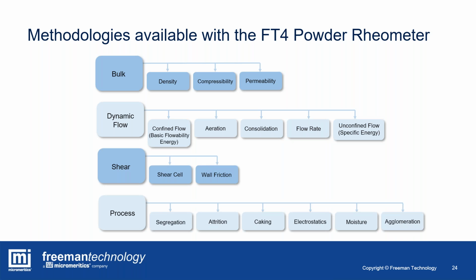And then finally, what we would call process type investigation. So propensity to segregate, particle attrition, looking at sensitivity to caking under different effects of temperature and humidity and duration. We can assess the effect of electrostatic charge within the material in terms of how the flowability changes. Same thing for moisture. And we can look at the effect of propensity to agglomerate, for example. So it really is a versatile instrument that allows you to investigate many different attributes of materials, or powders, and that's essential, as I'll show you in the second half of this presentation, where we're starting to look at a variety of case studies.